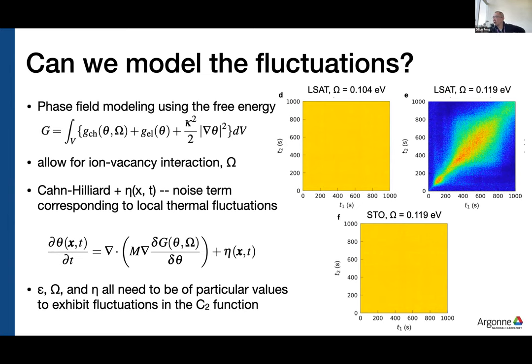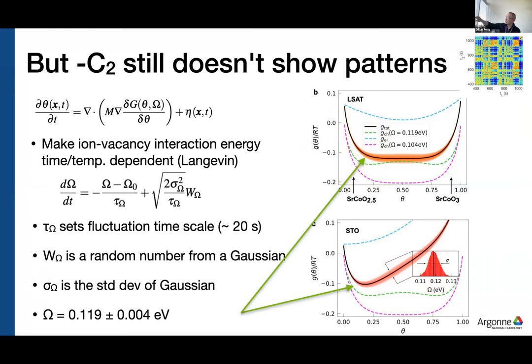So that's the eta term. And that corresponds to these local thermal fluctuations. And only if you have that noise term can you get this two-time correlation map I'm showing on the right, this blue one. But again, we couldn't replicate anything like what we see on the top right of this slide. So they then made a